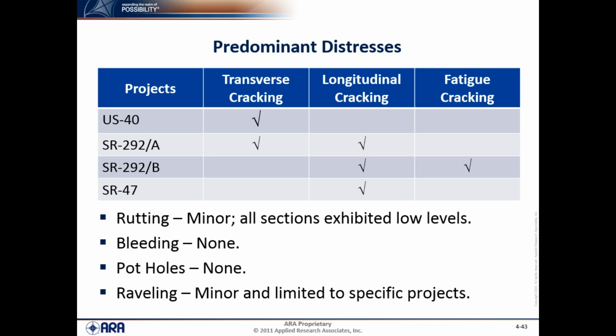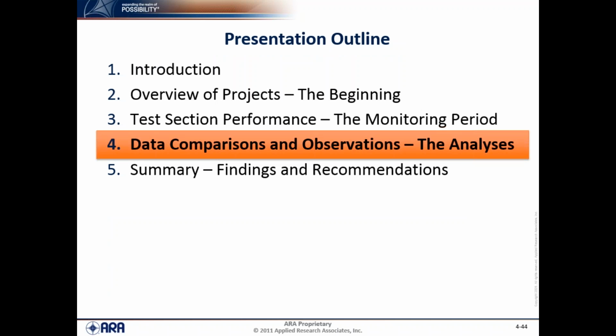Rutting was minor for all sections, all projects. Very low levels of rutting. Bleeding, no bleeding was noted on any of the test sections. Obviously, no potholes were noted on any of the sections or projects. We did note some raveling, generally minor, and it was limited to specific projects. But we didn't see it tied to the areas where we had identified truck-to-truck segregation before the sealers were applied. It didn't appear to be a one-to-one, so they were in generally different areas. But we did see some minor raveling limited to specific projects as well as to specific locations. And it was generally all minor.